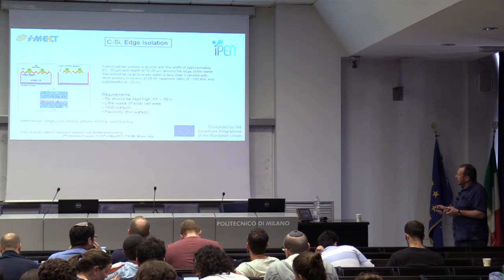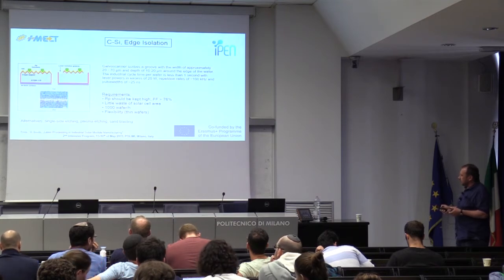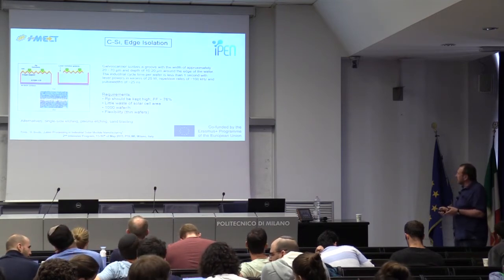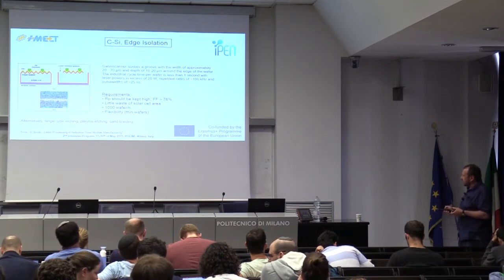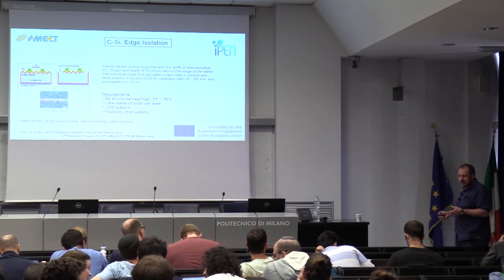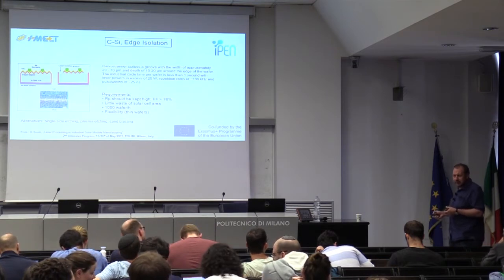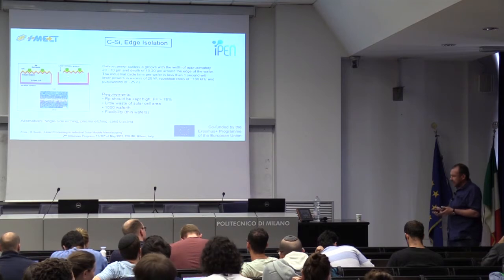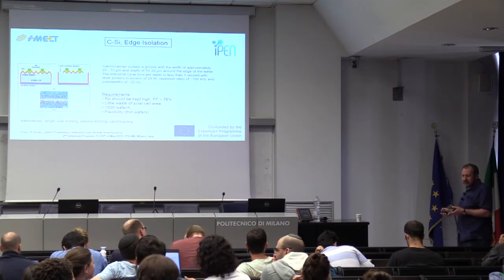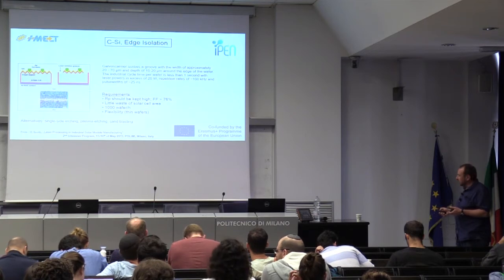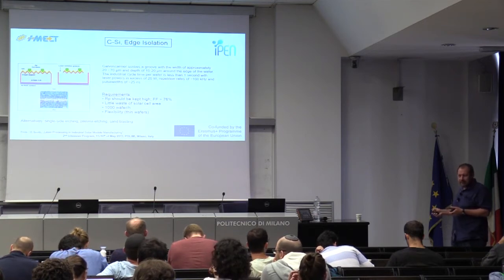Now, this is done usually with a galvanoscanner and either infrared laser. With silicon infrared, you don't need very fast or short pulses here. Picosecond, nanosecond lasers work very well. It can be done with infrared lasers. It can be done also with green, and now also with ultraviolet lasers.